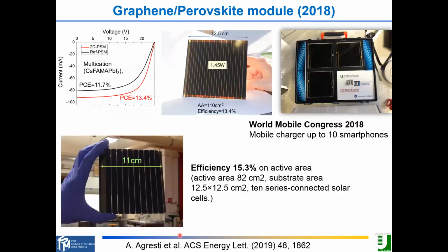And this is some example of module made with 2D materials control of the interfaces. And for example, this was something that was presented at the World Mobile Congress almost 3 years ago to recharge mobile phones. This is a module with 1.45 watt. The active area is 110 centimeters square. The efficiency on active area is 13.4%. And we were using 2D material, boosting the efficiency from 11.7% up to 13.4%.